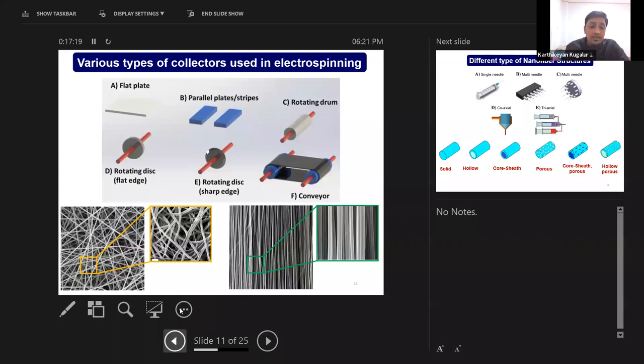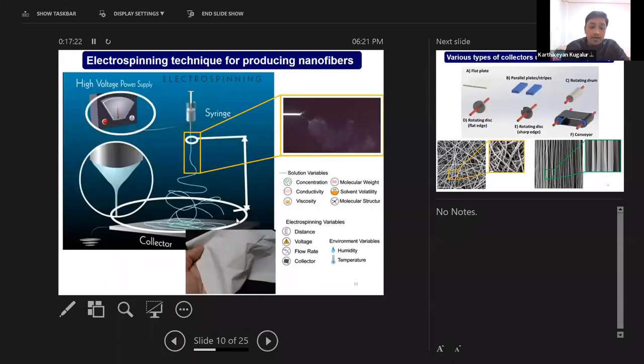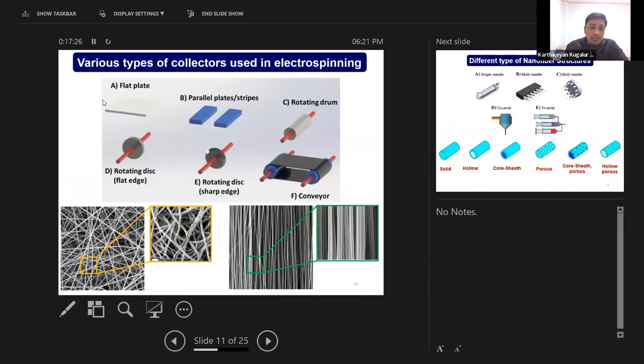And also, as I said, here we are using a flat type of collector, a plate collector. Instead of using this flat plate collector, you can use a parallel plate collector and a rotating drum. The drum will be rotating at a certain RPM so that the nanofiber will be deposited onto this. And also we have this type of collector and the conveyor type of collectors. If you deposit your material on the flat plate collector, the fiber will be randomly deposited. And if you use these kinds of collectors, rotating drum or flat rotating disc collectors, the fiber will be aligned in uniaxial fashion, and aligned nanofibers can be produced, apart from randomly oriented fibers.